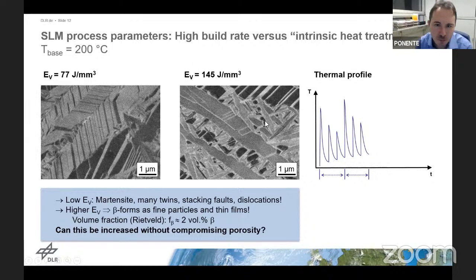effect be enhanced further if we further increase the volume energy density, or the laser energy amount that we put into the material, by changing the scan strategy? For instance, on the right-hand side, you see the thermal profile that we have by lasering a simple cubic specimen with 2 layers. You see this main spike at the beginning, and the second layer follows, and there's a buildup of the base temperature of the specimen.